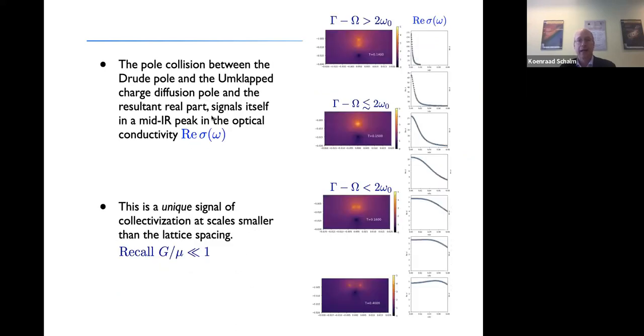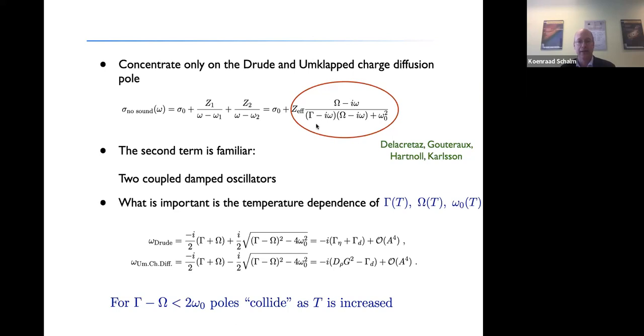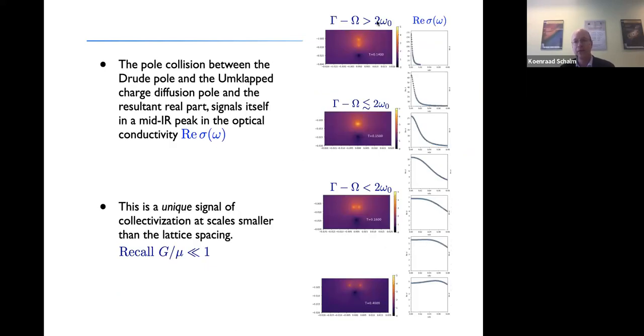Right? And this is again a slightly more detailed version. It's precisely when this gamma minus capital omega becomes smaller than 2 omega naught, that's the collision point where these two poles collide. Here you see in more detail a sequence of this collision, and you see how the Drude-like peak slowly transforms into this mid-IR type peak.